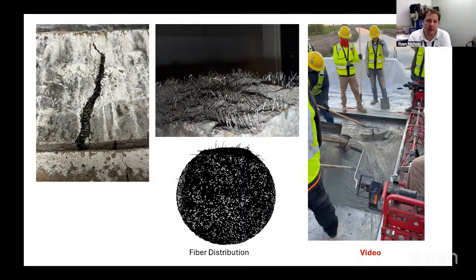A second question: you talked about, if I understood correctly, one of the differences is that with the fiber reinforced concrete, there's a lot more micro cracking versus larger cracking. I guess the question I have for you is, with a lot of micro cracking, is there not an issue with water infiltration that might corrode the steel fibers? If the steel fibers are small in diameter, any corrosion that occurs on them would seem to have a major impact, versus if there's some corrosion on a large diameter rebar, it takes a long time for that corrosion to start having a big impact on the structural integrity of it. So talk to me about the micro cracks and the water infiltration, and how does that affect the steel over a 40-year service life like you're talking about?